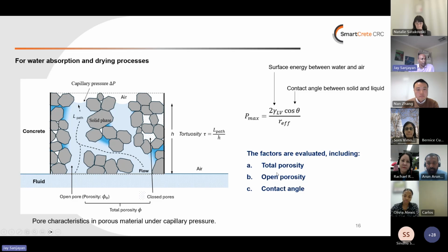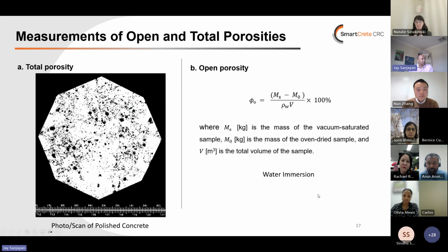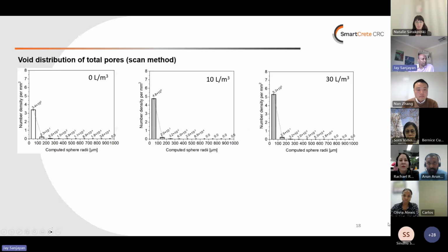is related to the porosity. It's the radius of the pore. So we measured the total porosity by scanning the concrete and doing an image analysis. That method has become quite popular. That measures the closed porosity and open porosity. And the open porosity is measured by water immersion. So we immerse it in the water and calculate how much water is absorbed into the concrete, and the water only gets absorbed into the open porosity. And this is the pore size distribution we got.